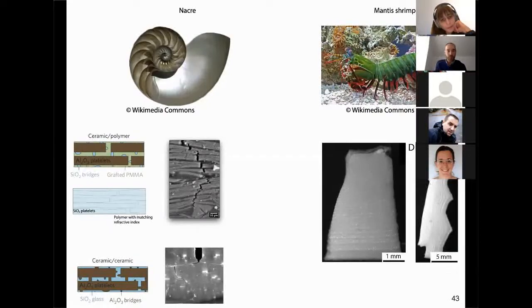Whereas when we put something that is just mineral, so ceramic composites, we end up with very high deflection when we try to propagate a crack inside the sample. And that's what brings the toughness. So we change the reinforcing mechanism just by changing the mineral content of this ceramic. And finally, something we've been playing with a bit more recently is mimicking the microstructure of the hammer of the mantis shrimp. We managed to make dense ceramics that have periodically varying grain orientation inside the microstructure, and so hopefully these will also be a bit more impact resistant, which for ceramics is also quite an interesting field. Not only is toughness good.